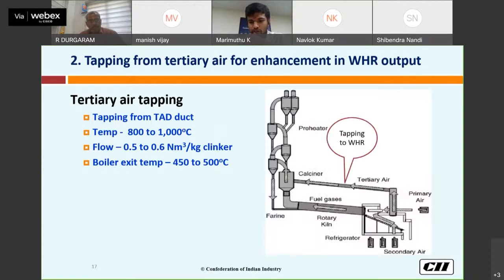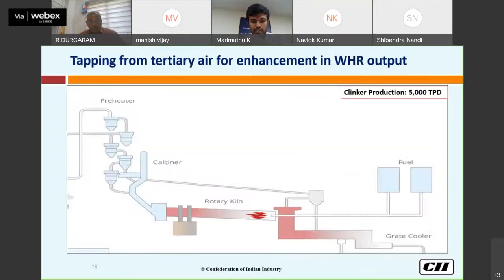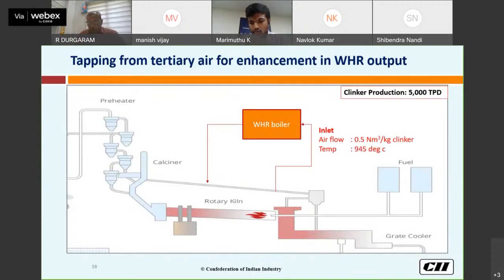So this is the normal circuit. This is the area for tapping for WHR, between the clinker cooler hood and the calciner, where the tapping is taken. So this is the circuit for the WHR boiler. The inlet condition airflow is around 0.5 Nm per kg, temperature 945 degrees, and in the outlet condition the airflow is the same and the temperature is 460. So this is a drop in the WHR. The output we get is around 4.1 megawatt.